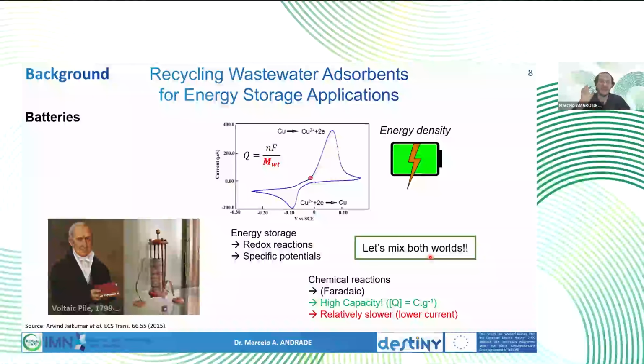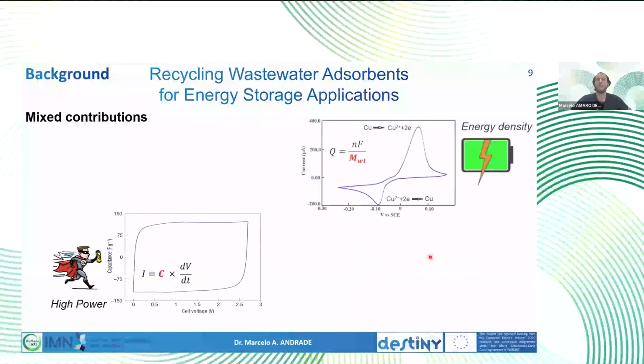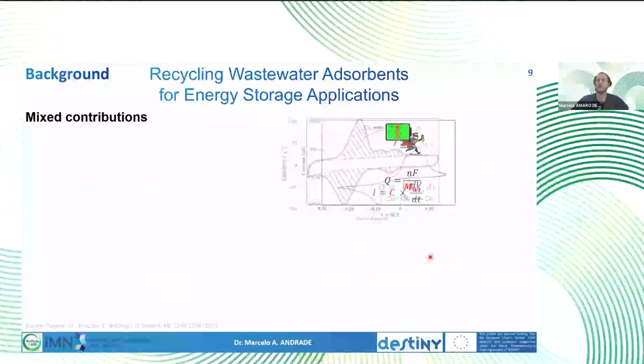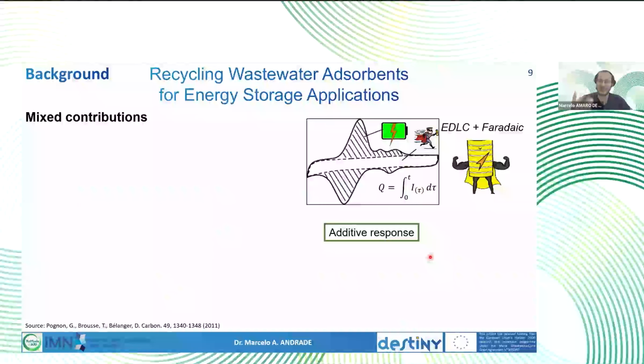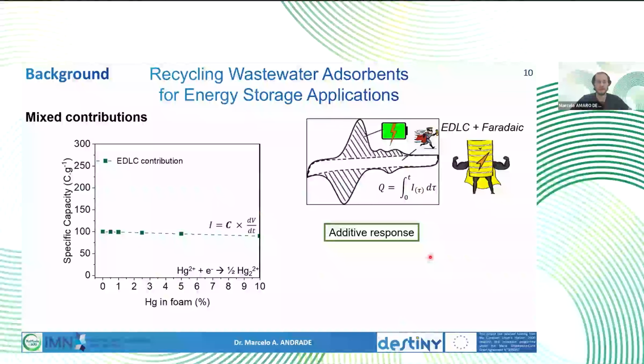So the idea here is to mix both worlds, where you can store energy chemically, with the battery-like behavior of metals undergoing redox reactions, and on the surface, with the high surface area of the carbon-based material. When you have these two contributions, what is expected is an additive response, all that in theory, between the supercapacitor type reaction and the Faradaic one, which is the energy coming from the redox of the metals.